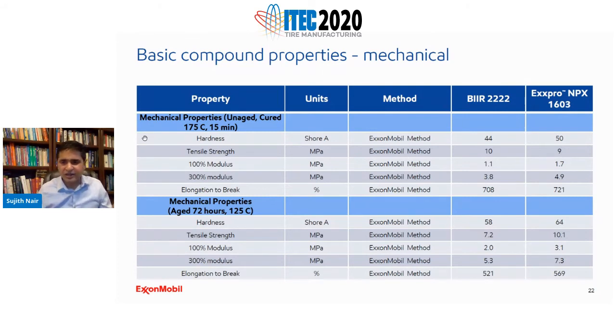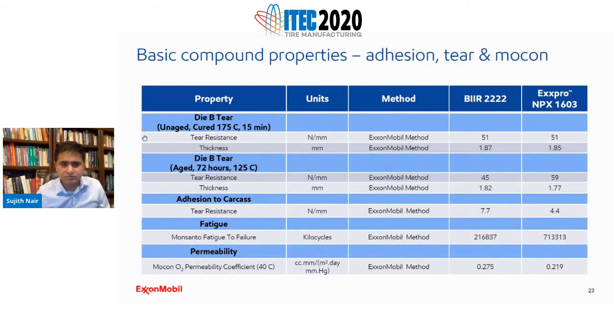So you can see that the change in tensile strength of bromobutyl was around 28%. It's a 28% reduction in the tensile strength of bromobutyl, whereas in the case of X-Pro, it's equal or slightly higher, because there's obviously a little bit of uncross-linked parts that keeps on cross-linking. But in case of X-Pro, we have always seen that the mechanical properties are maintained.